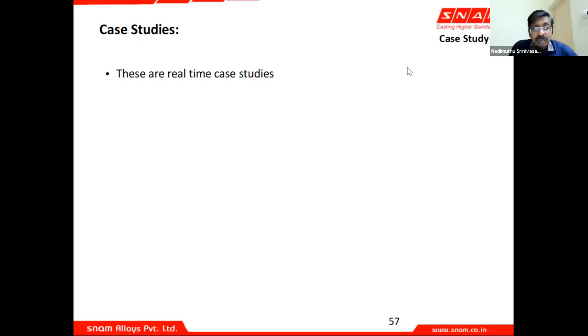Correct. See, wherever, as I told you, a customer has provided us a condition, we use the same charge mix. But whenever in our R&D center we do our trials, like the size standardization trials, we use anywhere between 10 to 20% pig iron and around 30 to 40% of CRCA, and the balance is the returns. So this is how we normally do here.